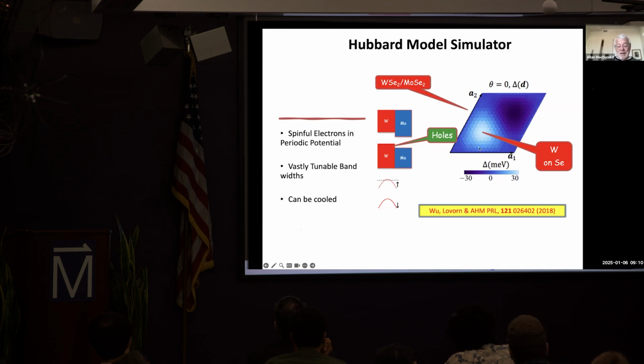And so I get an effective potential, which in practical cases, of course, in these hetero-bilayer systems, the lattice constants in the two layers aren't exactly the same. So that's another way in which the reciprocal lattice vectors differ. And it turns out in the end that typically, the moiré periods are on the sort of 10 nanometer scale that I mentioned. So in the end, in this system, you just have an effective potential that's periodic, has a size of 50 meV or so.